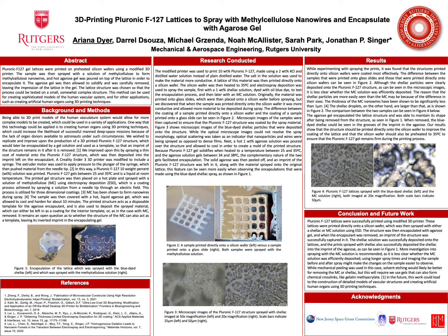The agarose gel encapsulated the Pluronic F127 lattices successfully, as it was able to maintain the shape of the structure after it was removed. In addition, the blue-dyed shellac could be seen in the grooves of the imprint in the agarose after it was removed. This means that the shellac solution was successfully transferred from the Pluronic F127 structure on which it was sprayed to the agarose encapsulant.